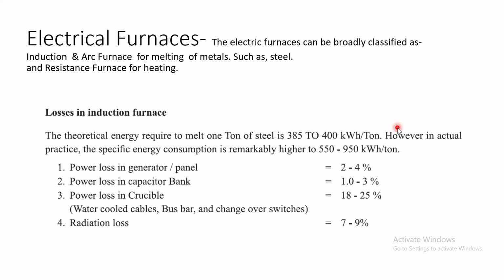Many industries have got 420 or 430, then we can say that there is a potential to drop this electrical consumption to this level. That is why this level is called the benchmark energy consumption for melting of steel. However, in actual practice, the specific energy consumption is remarkably higher, 550 up to 950 kilowatt hour per ton. Nowadays, many industries have reached a level of around 450 also, by using various measures of saving energy, or by applying the recommendations given by certified energy auditors and so on.